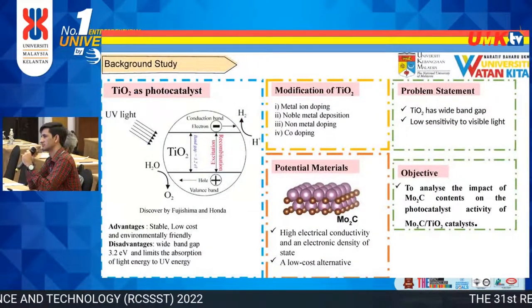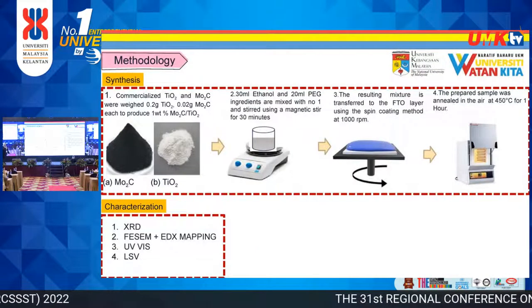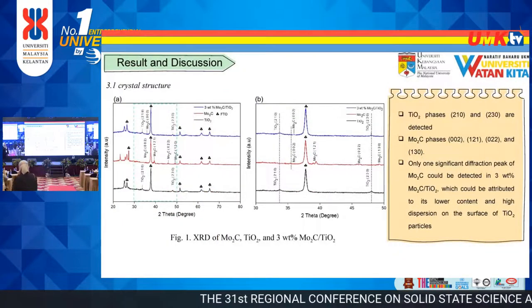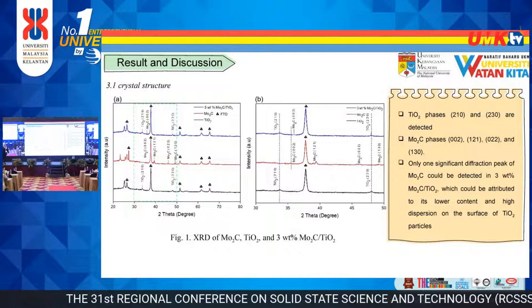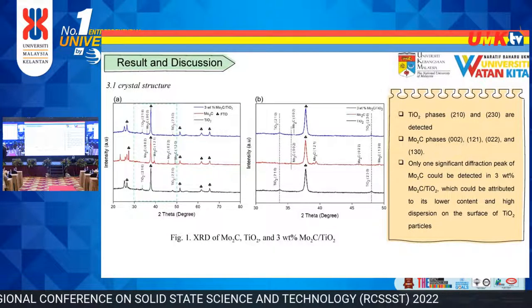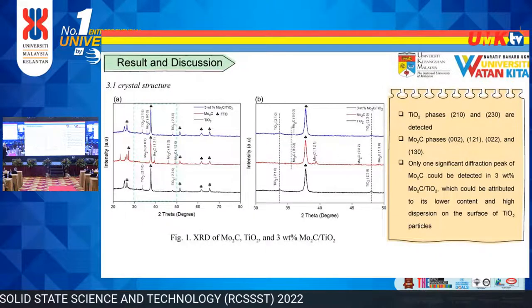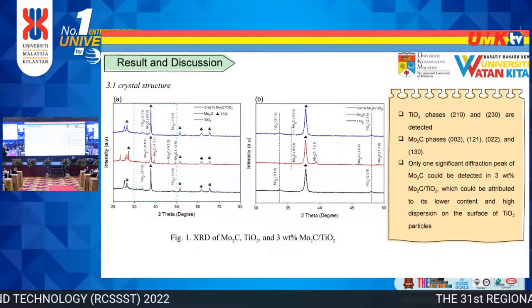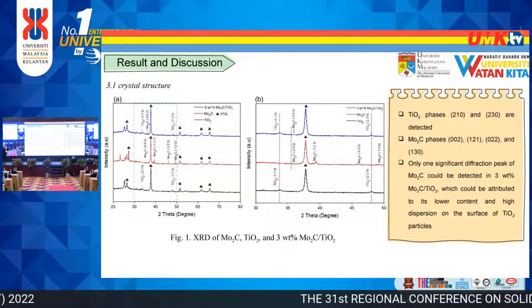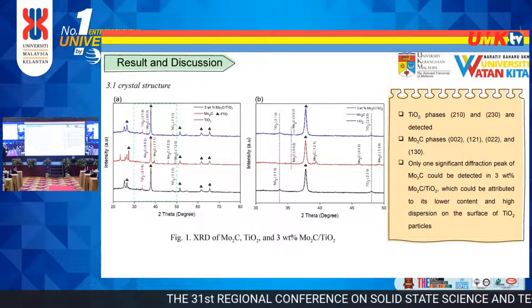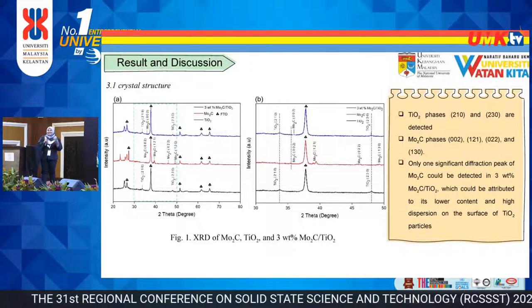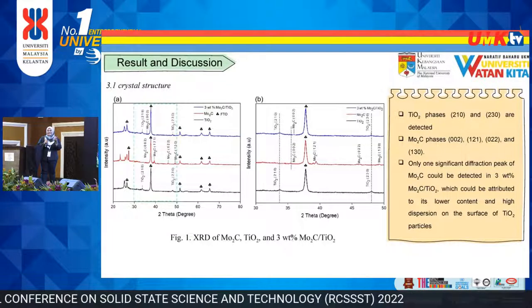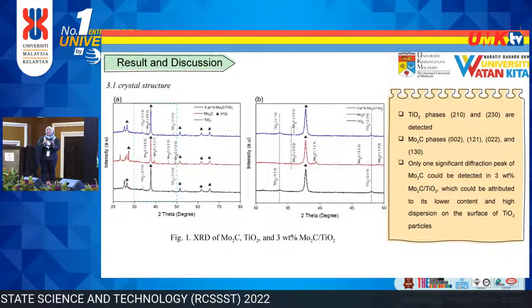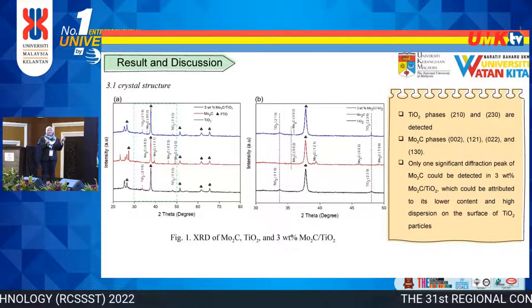This is because this is a preliminary study. As you can see from the XRD, there is a very low intensity of the peak. This is because I'm using the spin coating technique, so I have a thin layer of the sample. I have been improving the method to improve the intensity, to find the main peak. I want to find the main peaks.